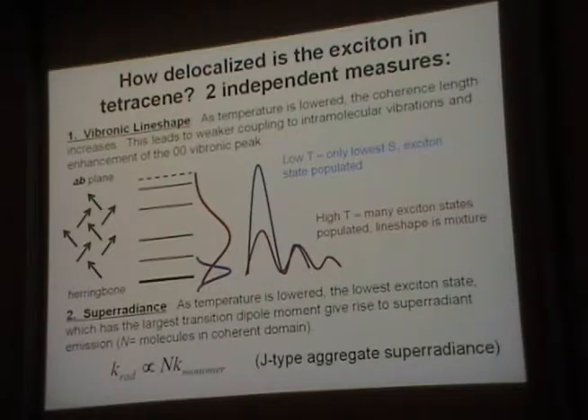So this is a case where electronic states have a Boltzmann distribution, right? You're not used to thinking of Boltzmann populations of electronic states, but in these coupled systems, you do have that. And when you lower the temperature, you lower the Boltzmann population, you condense it into the lowest exciton state, if you go to 4K. And that means that, at room temperature, you get a fluorescence spectrum that's a mixture of all the fluorescence spectra of all these electronic states in the band.